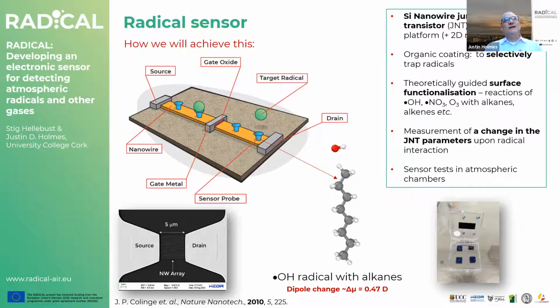Now, this functionalization that we're doing on these nanowire surfaces is guided by our theoretical calculations. The group in Athens, Leonidas, I should say, has looked at reactions of hydroxyl and nitrate radicals and ozone with different alkenes and alkynes to try and maximize the dipole moment change that we can detect electrically. Now there's a video here, I don't know if it'll work, of some of the simulations. This is looking at hydrogen extraction, but he's looked at different silicon surfaces and silicate surfaces and how molecules and radicals interact with these surfaces. So once we have this functionalization layer, we react with radicals, we get a dipole moment change, and we then measure these different parameters.